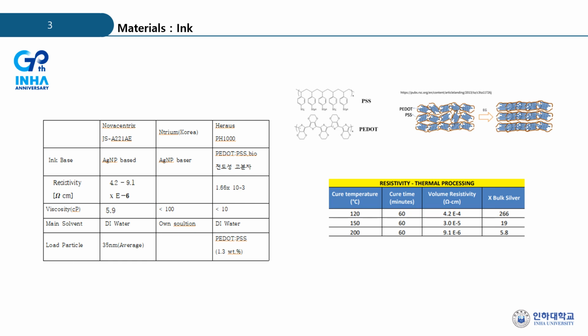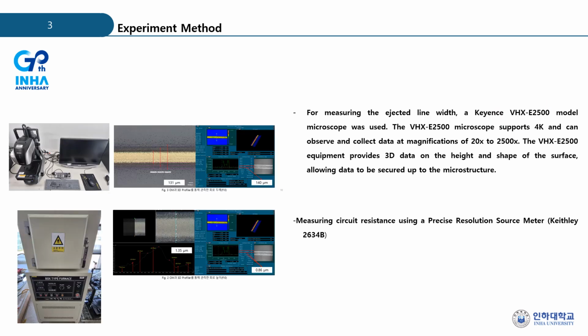Materials and ink. Nanoparticle ink and the conductive polymer PEDOT were used, and EG was added to them to enhance the conductivity. These are the specifications for each ink. This is the experimental method to measure the exact line width.